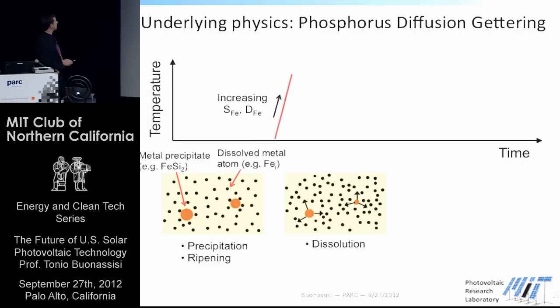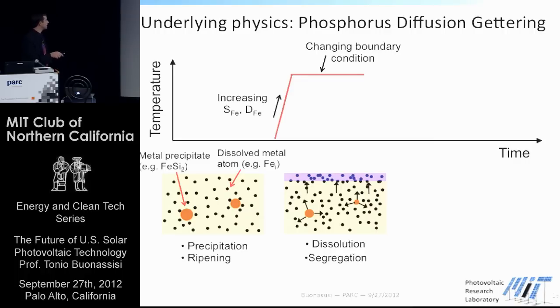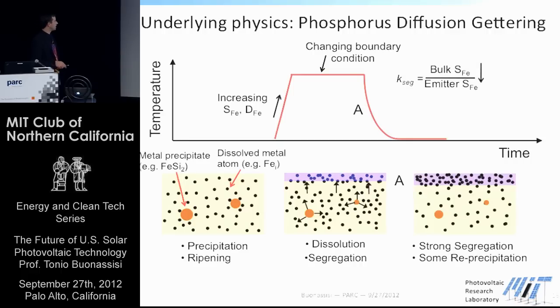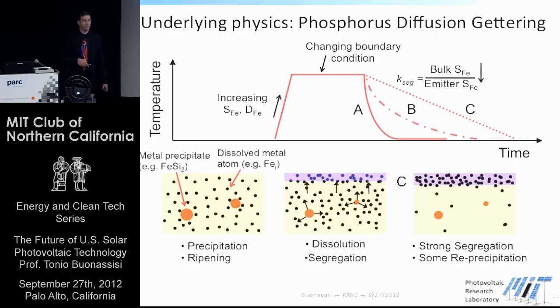And as we heat up the sample to do this phosphorus diffusion step, these precipitates begin dissolving. The solubility for iron increases within the bulk. As we begin annealing, the phosphorus diffuses into the wafer, forming that junction region. It actually has a higher solid solubility for the iron. The iron begins being attracted to that layer. And as we cool down back to room temperature, the solubility drops again, and the segregation coefficient decreases, and we have a depletion of iron point defects within the bulk, an increase of their concentration up here in that layer. We're sweeping the iron out of the device. And depending on how we cool, we get a different final distribution of the iron, which is nice. We can control the iron distribution.